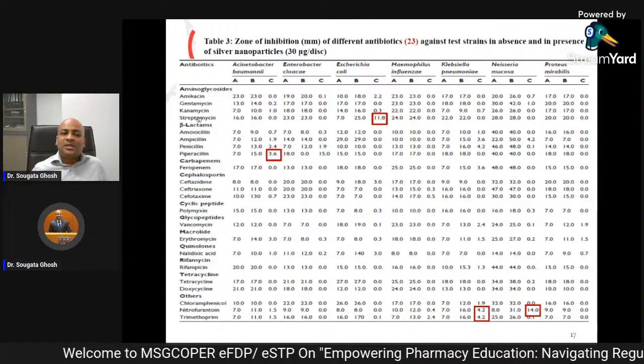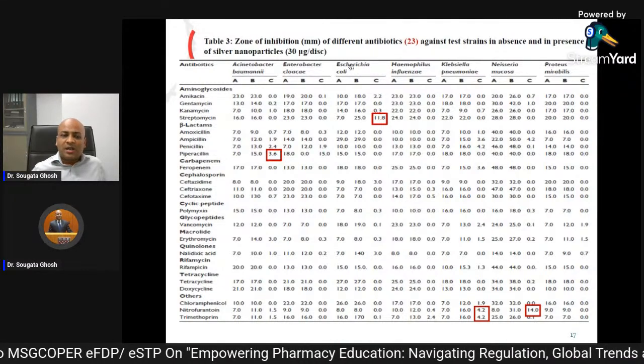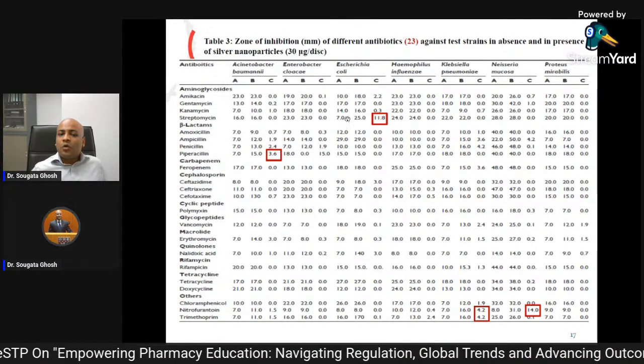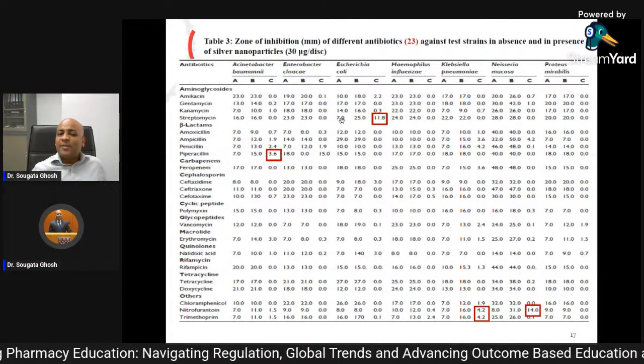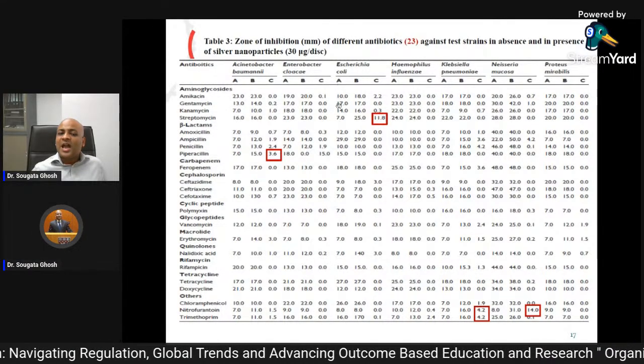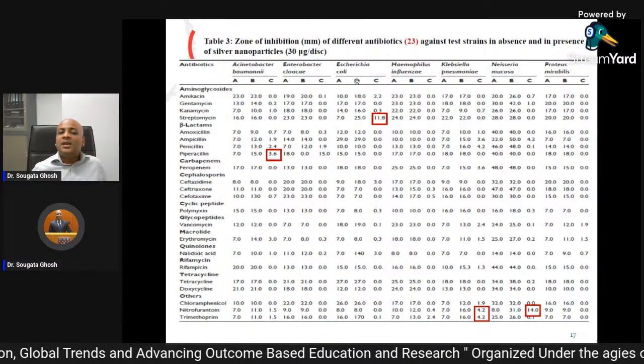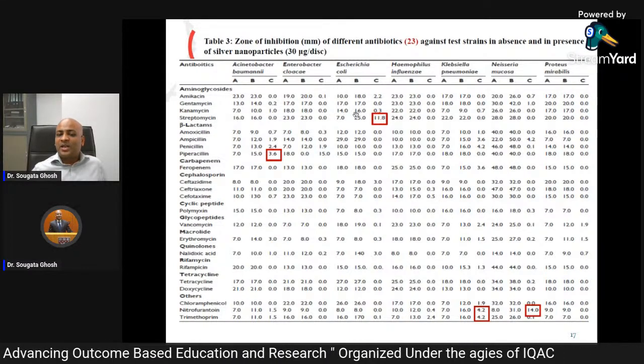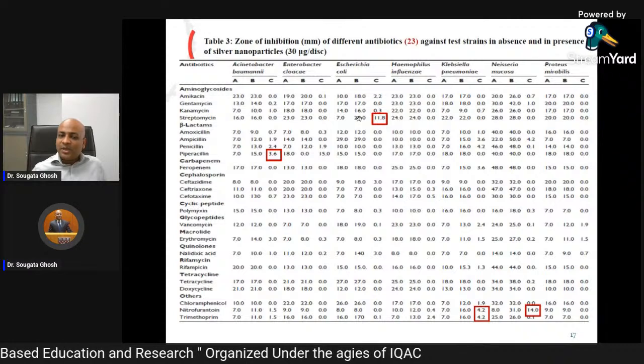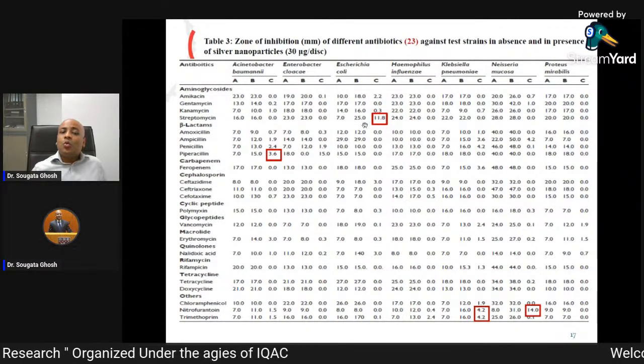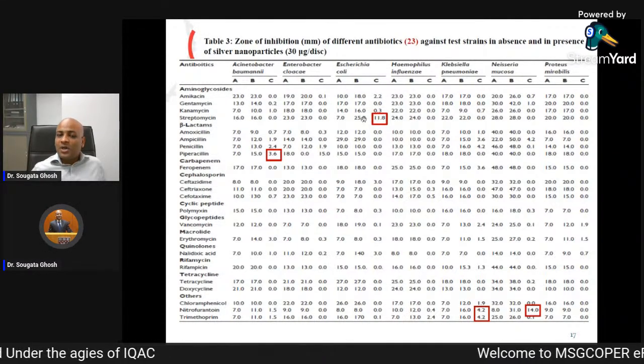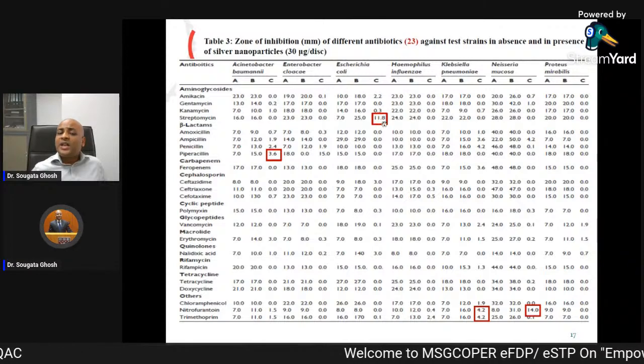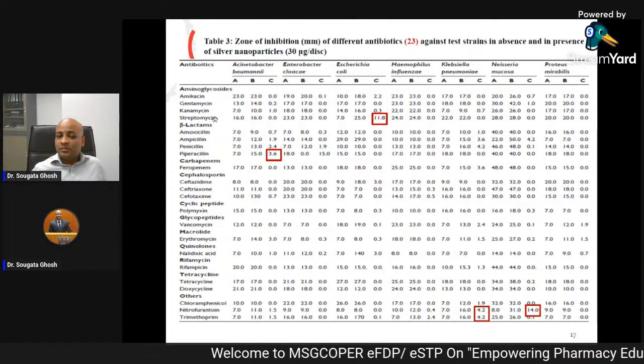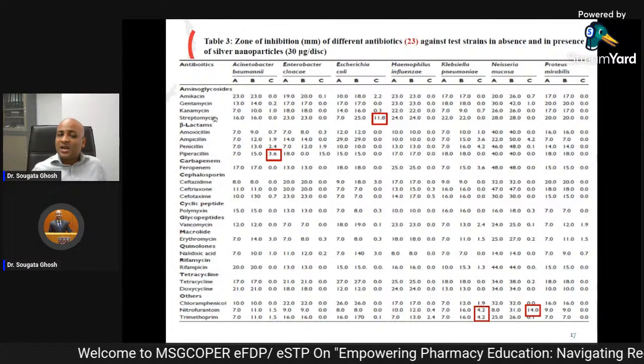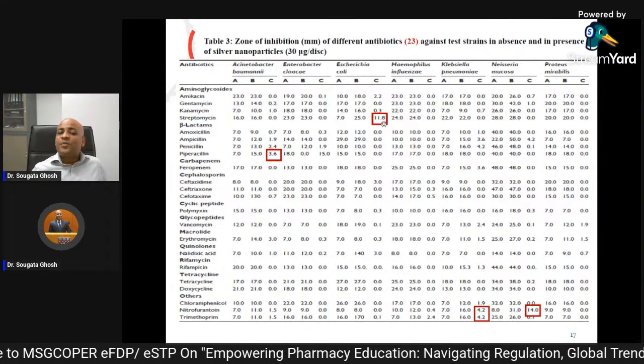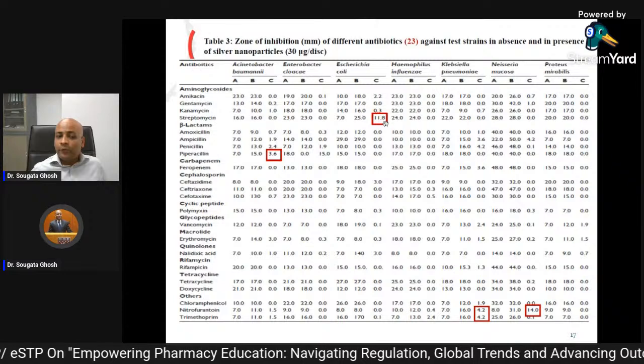And you can see streptomycin with silver nanoparticle. Only streptomycin over here shows a 7 mm zone diameter. A is only antibiotic. B, streptomycin plus silver nanoparticle, 25 mm diameter. C, what is the fold increase? It is not times, fold increase. So 11.8 fold increase for this streptomycin. You add silver nanoparticle and streptomycin becomes 11.8 fold more powerful.